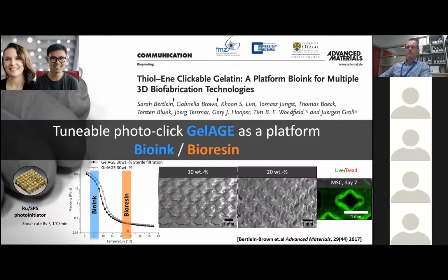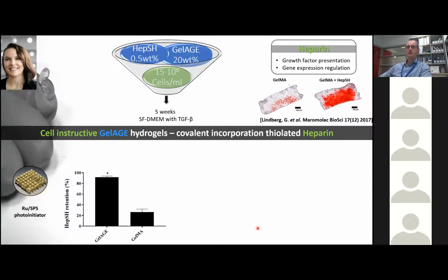Likewise, when we also then started looking at room temperature, which is generally where all the different lithography-based systems work, again with visible light, we showed that we could have quite a favorable rheological profile. So again, low viscosity, which made it ideal as a bioresin. So we could also show with these GelAGE materials, we could get high resolution DLP structures and good cell viability. So that was a really exciting finding, and that then tried to show the capability of this sort of photoclick chemistry, and showed us that we could actually have one family of materials that could start to be used across multiple biofabrication technologies.